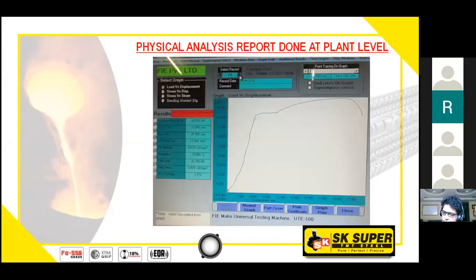This is basically the computer print of the physical test. If you see on the right hand side, the tension test bar size is 10 mm. This typically is a graph of how the steel reacts after putting pressure. If you understand this graph very carefully, once I start to apply the load from 0, it goes at an angle of 80 degrees to a point. This point where it turns right from 0 to this point is the elastic stage.